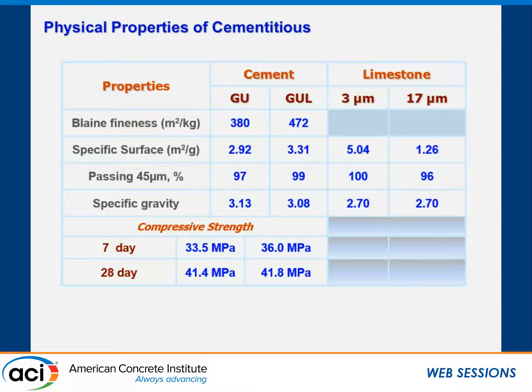That lower specific gravity of the interground limestone cement changes your paste content if you do pound-for-pound replacement rather than volume replacement. Doing things by volume, as Dale did, is really the right way — but in real life it's very rare that people are that sophisticated. Most just go pound for pound and look at performance. The two cements were designed to have equivalent compressive strength, and they do.